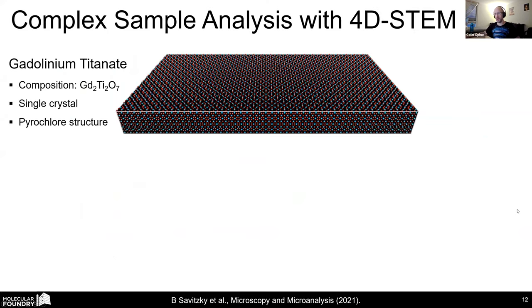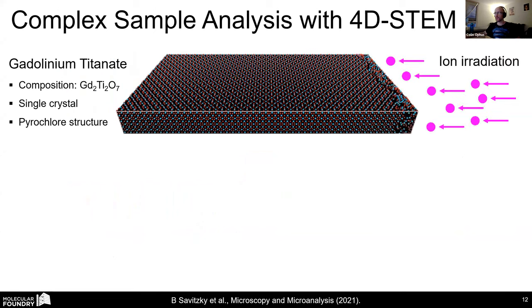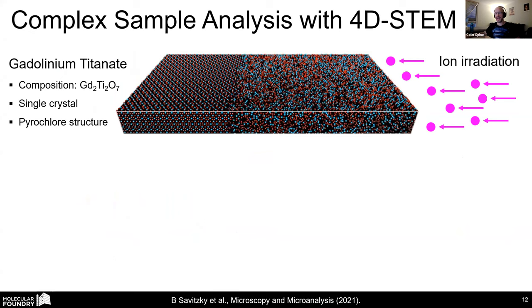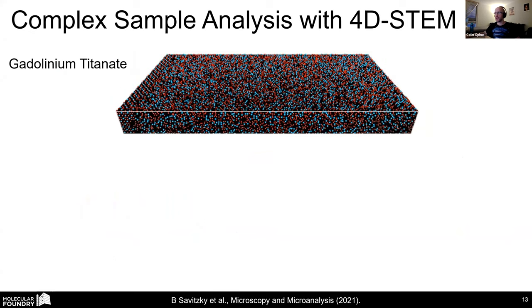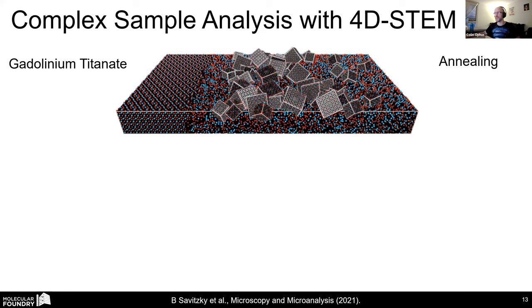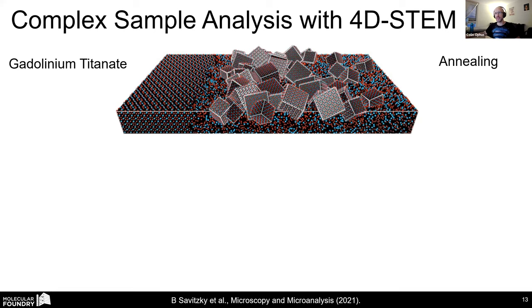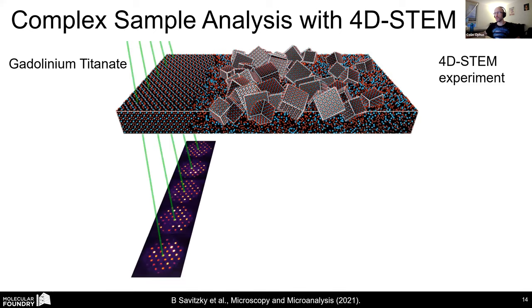So let me show you an actual experimental example. This is a user project, gadolinium titanate, perfect single crystal. They put it next to a reactor, ion irradiated it, and this amorphizes it down to a depth into the material. Then they popped it into a furnace to anneal it, and you regrow from the crystalline front into the amorphous region, but you also nucleate all of these randomly oriented crystallites here. The parent crystal had pyrochlore structure, but the recrystallization is much more like fluorite. And these recrystallized tiny grains in the middle that nucleate are fluorite as well.